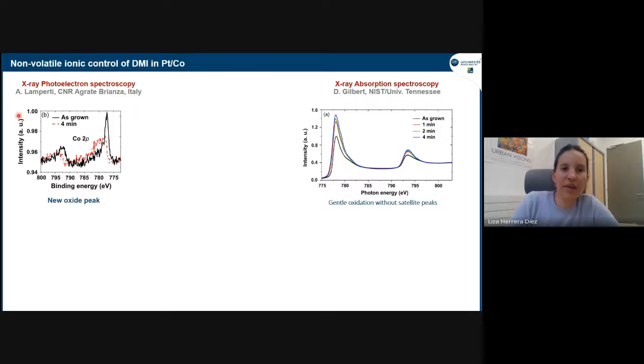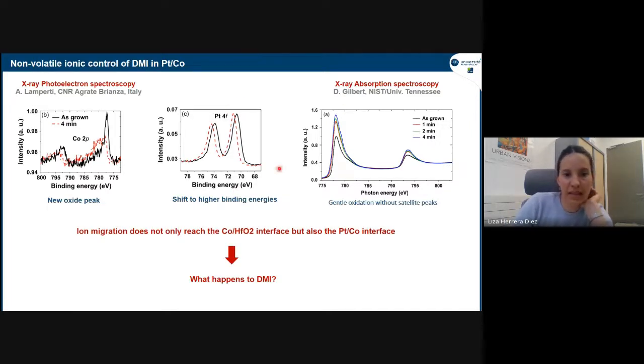So we could nicely see by X-ray photoelectron spectroscopy with our collaborators in Italy that there was indeed a signature of oxidation of cobalt. It was the same as what we observed from XAS done by our collaborators at NIST. And what was interesting at this point is to look at the platinum. Then we could see that there was a shift in the peaks of the platinum. So we couldn't see an oxidation of the platinum, but we could see that there was some kind of change in the chemical environment of the platinum.